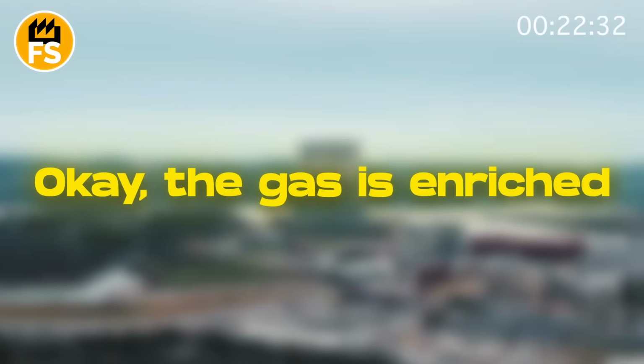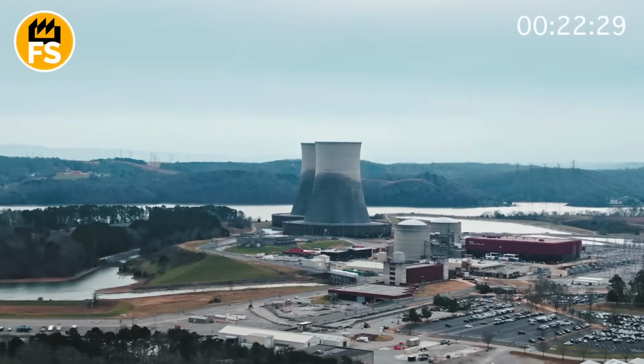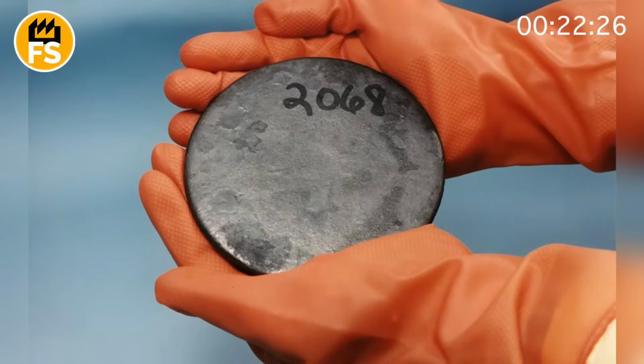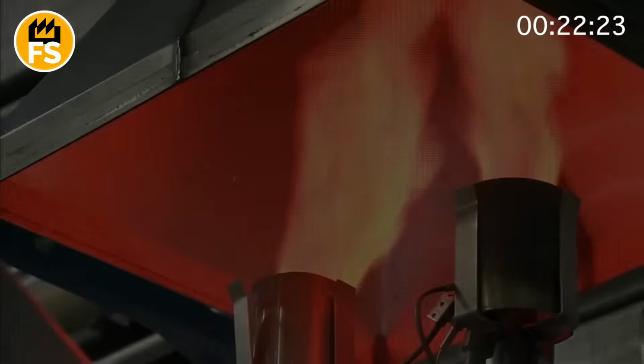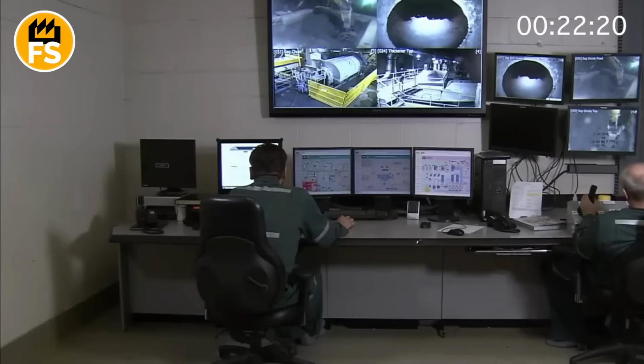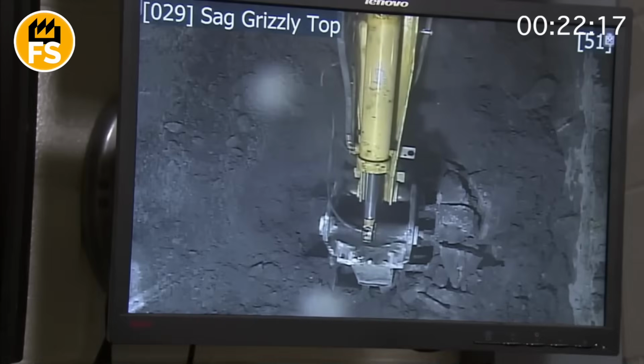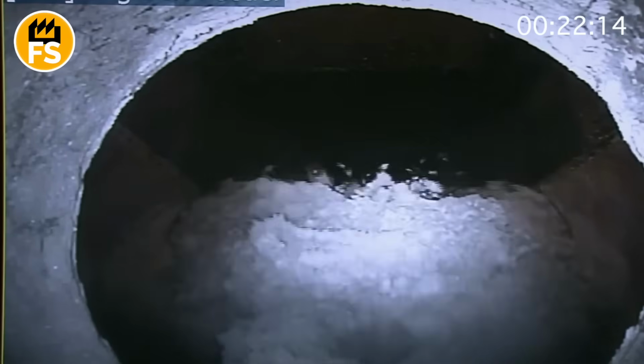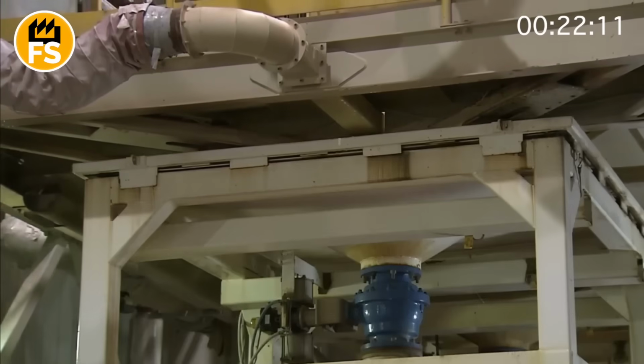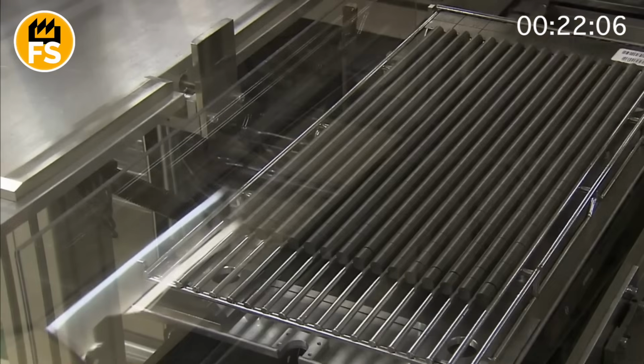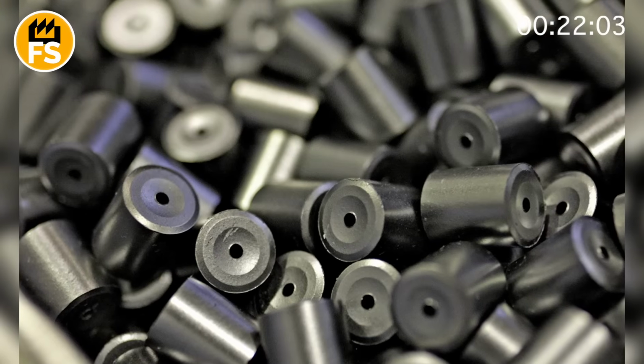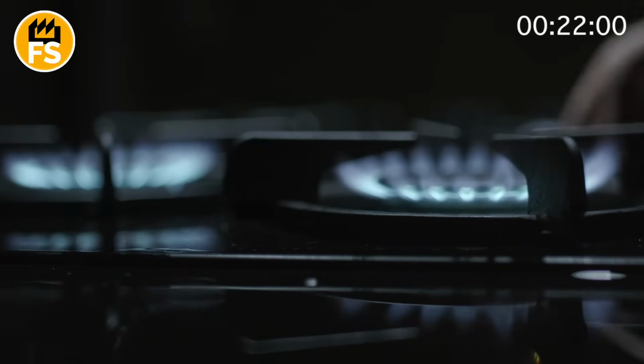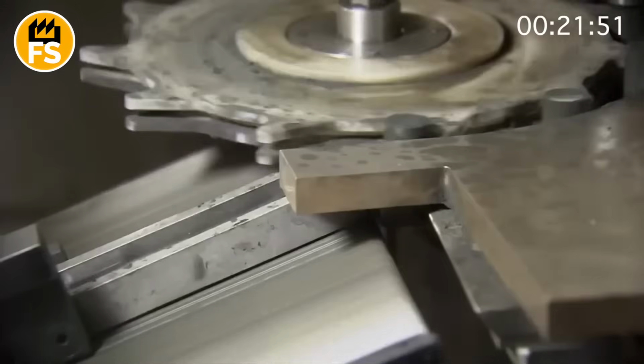Okay, the gas is enriched, but in its gaseous state, it won't feed a reactor. So now it's converted again, this time into a solid ceramic form. After a series of chemical reactions with hydrogen, oxygen, and ammonia, the gas becomes uranium dioxide, a solid substance with a dark gray color. This powder is pressed under a pressure of 20 tons into small cylindrical pellets with a diameter of 3/10 of an inch. They look almost cute. But each such pill is like a charge of energy equivalent to 17,000 cubic feet of natural gas. Next, the pellets are sintered in furnaces at almost 3,000 degrees Fahrenheit to make them strong, like porcelain.